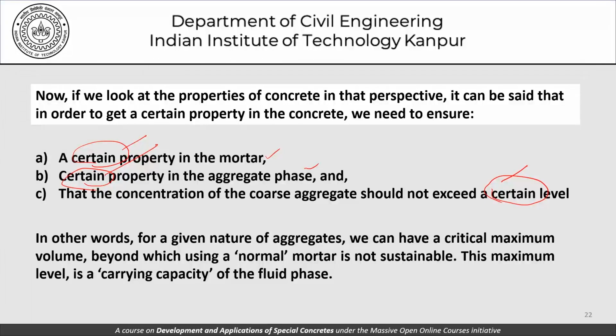In other words, for a given nature of aggregates, we can have a critical maximum volume beyond which using normal mortar is not sustainable. This maximum level is a carrying capacity of the fluid phase. We'll probably look at it at some point in time, either today or maybe in the next lectures, how did we proportion a concrete mix? We proportioned it by first determining W, the water content based on workability. Then we added cement to the extent that is required using the water cement ratio relationship. And then we said that we will divide the remaining volume between gravel or coarse aggregate and sand, which is fine aggregate, using the concept of S/A, that is the sand in the total aggregate volume.